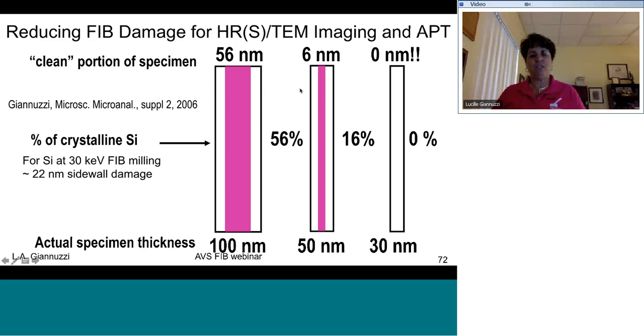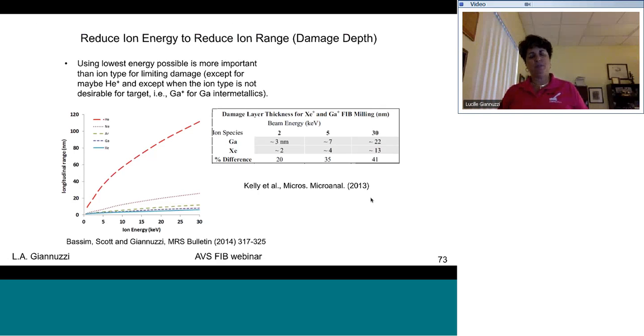If we continue to get this sample thinner and thinner, obviously we're going to get to a point where the entire sample is just amorphous damage. So what I like to do then is to start with a thicker sample. Let me go back first and talk about what's the impetus then for doing low energy polishing. We can reduce the ion energy, which reduces the ion range, which also reduces the damage depth.